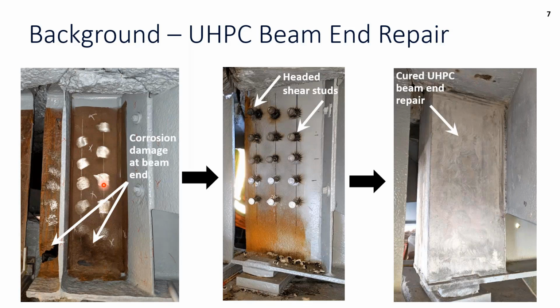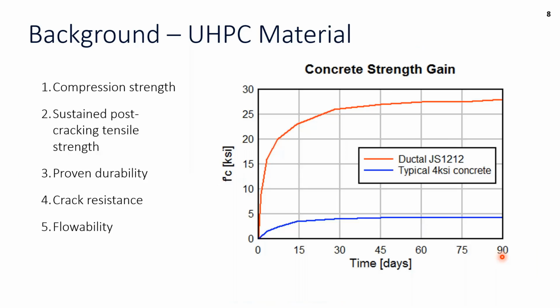After that, go back and weld the headed shear studs to those intact portions, so leaving that bottom alone. Then we cast and cure our UHPC and go ahead and remove that formwork. And you can see we're left with a really simple end block of UHPC, and we're able to effectively translate those bearing forces. Some of the background on the UHPC material.